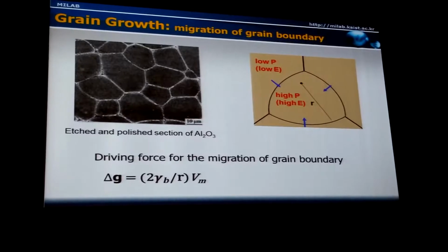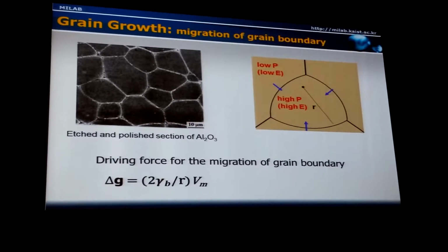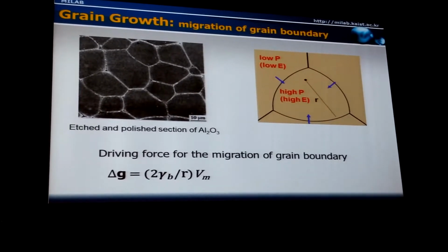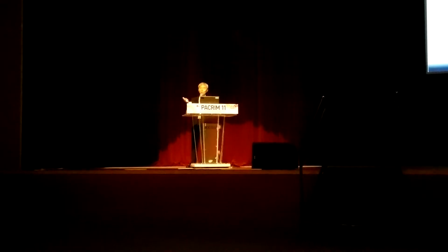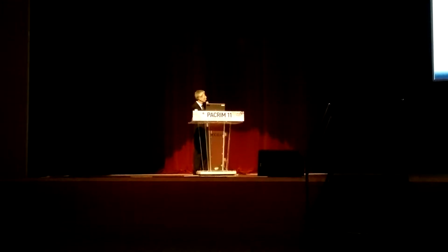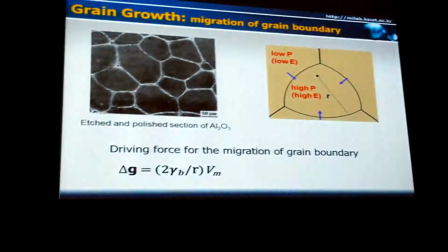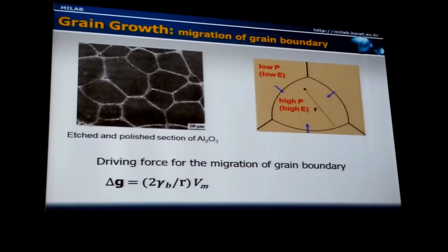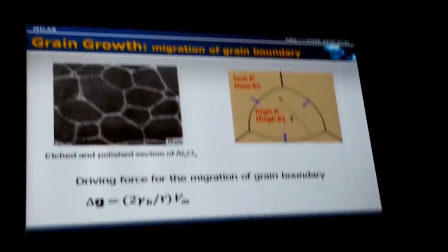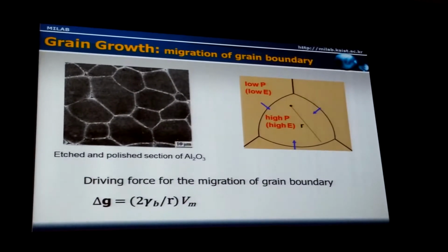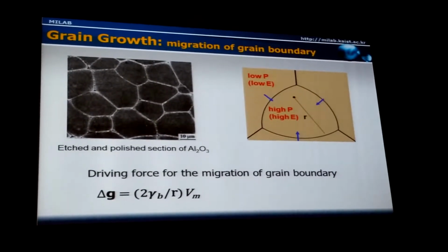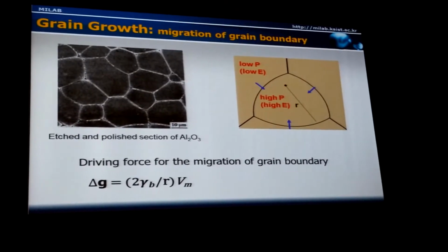When you look into a two-dimensional microstructure, as the grain sizes are different in the sample, there must be a non-zero curvature between adjacent two grains, as shown schematically here. Because of the non-zero curvature, and in effect because of the size difference, there is a capillary pressure difference between two adjacent grains.